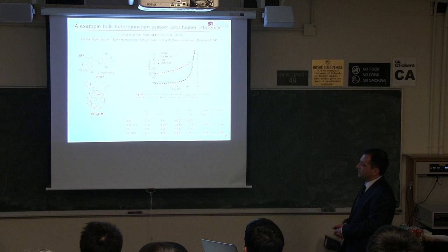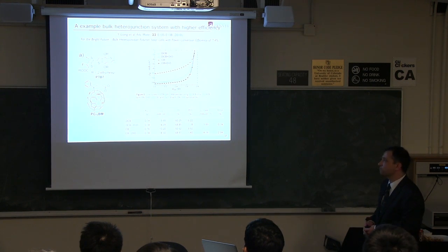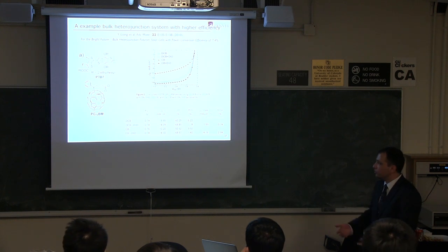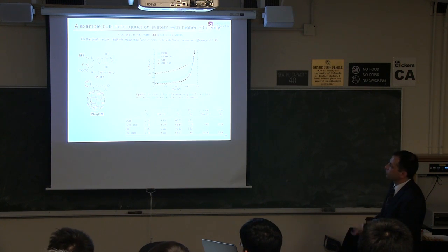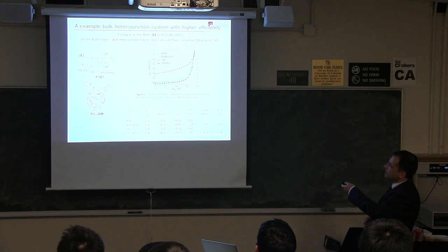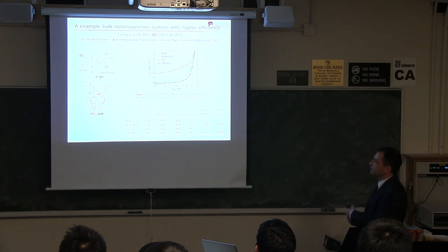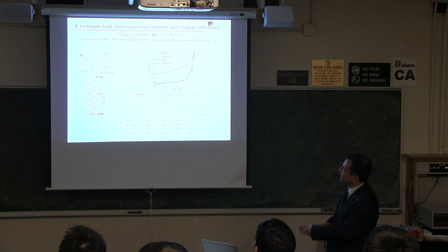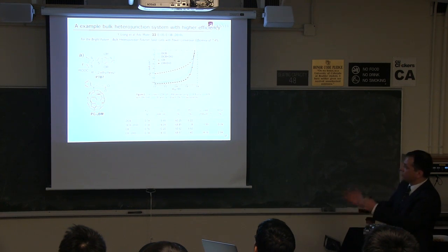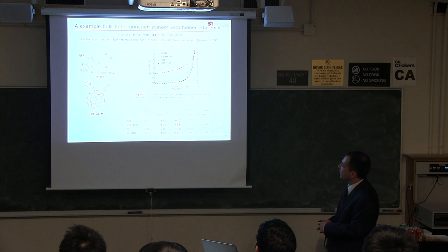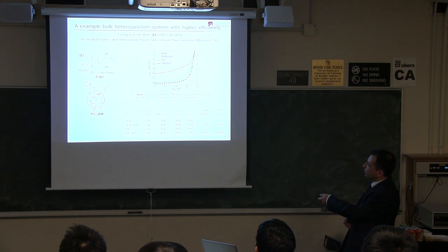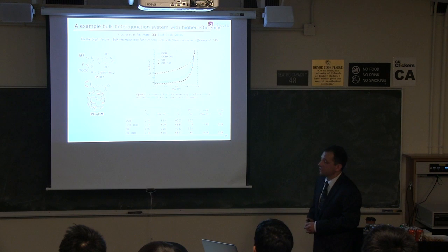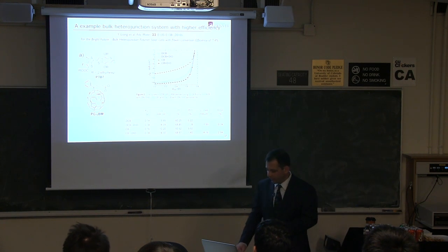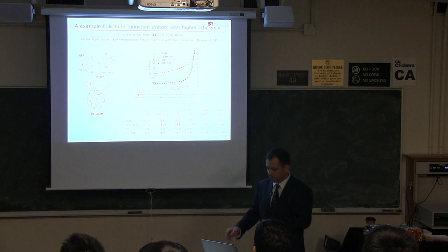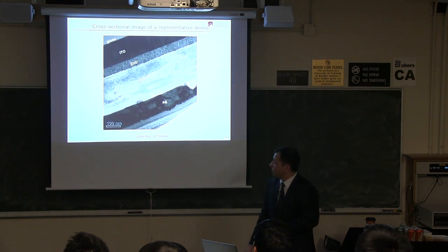One thing I want to point out is that the mixing of the donor acceptor is very important. And how you control the mixing depends on the solvent you use or mixture of solvents. So for instance, dichlorobenzene versus chlorobenzene. And you might add in a co-solvent, which is diiodooctane, which is funny because I think that's the Latin word for God. So if you put a little religion in the device, it works very well. But if you use chlorobenzene with this DIO, you can get a 7.4% device. So there's a little bit of magic in how you actually formulate the morphology, the mixing of the donor acceptor phases. What does that morphology look like?